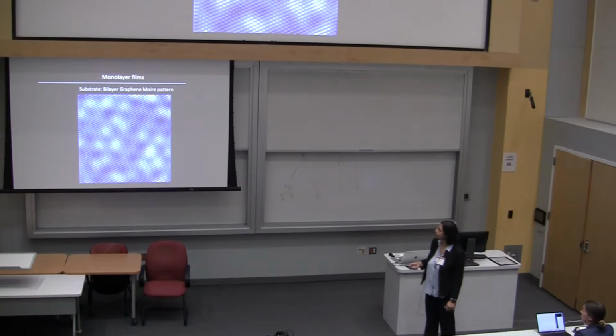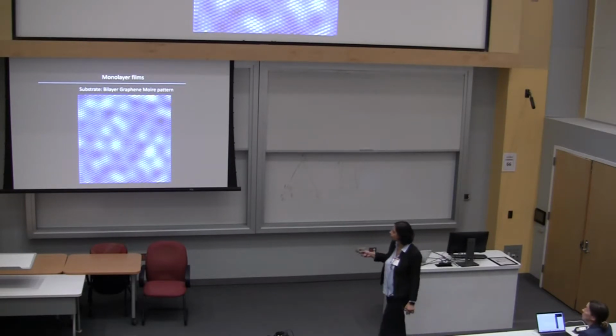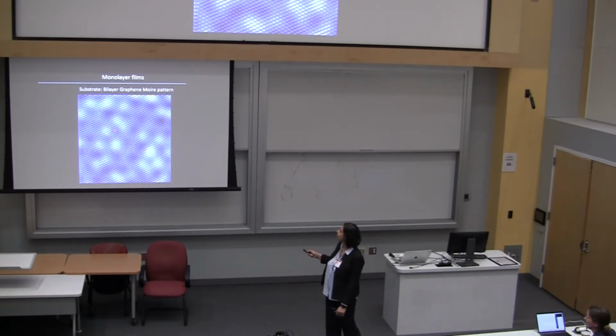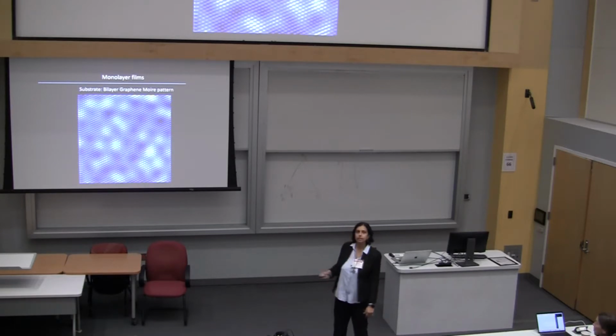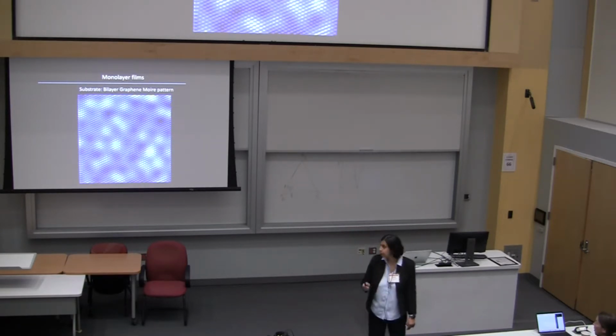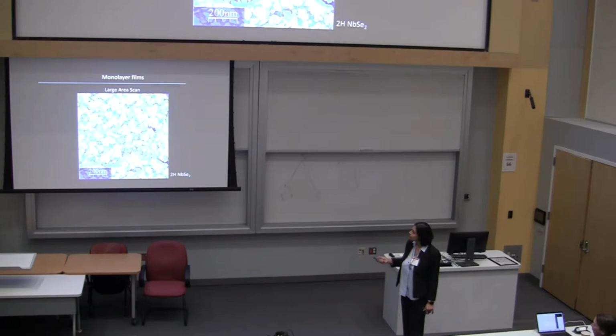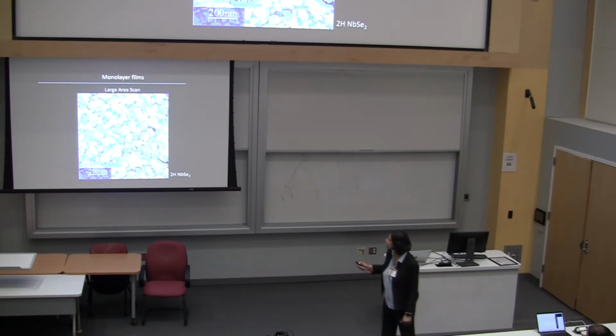Okay, so here's what our substrates look like. This is actually one of our substrates. This is bilayer graphene. You can see the bright and dark spots. That's the moire pattern that you expect from bilayer graphene. This is, for example, 2H niobium diselenide. This is a pretty large scan. And you can see it grows really well, right? This is probably 2 layers. Maybe one of these very light ones might be a single layer.